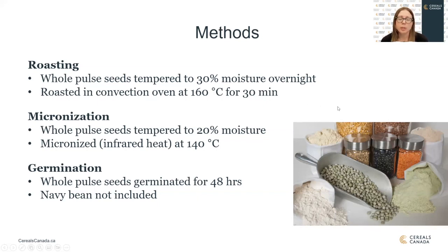We tempered the seeds to 30% moisture and roasted them in a convection oven at 160 degrees Celsius for 30 minutes. For the micronization treatment, the seeds were tempered to 20% moisture and then micronized at 140 degrees Celsius. And for germination, the seeds were germinated for 48 hours. You'll notice that navy bean is not included in the germination treatment, as a kind of microbial slime got produced during that treatment, which made it not able to be milled. These treatments were selected from some of the work that Mike Nickerson's lab did initially. They did a bunch of different conditions, and these ones were pulled out as the best ones to do scale-up studies on at our facility.